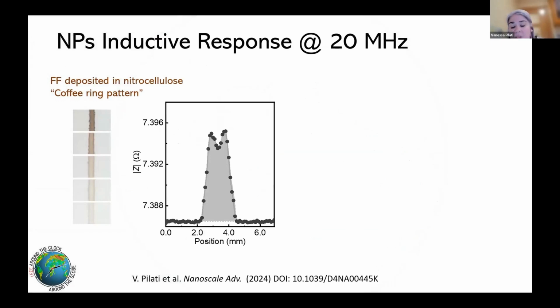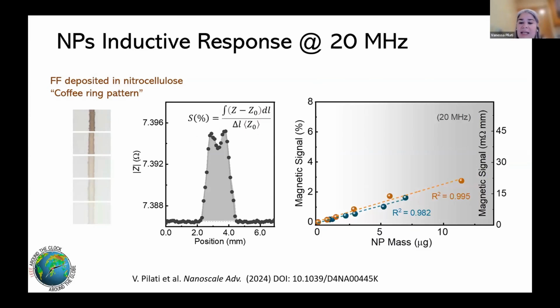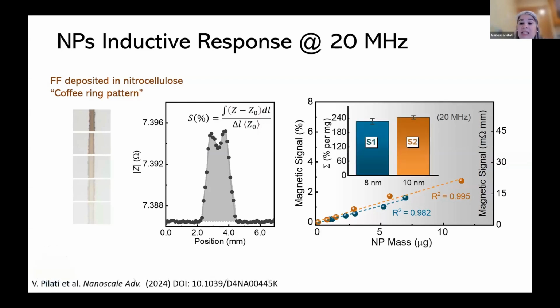We printed different lines, different concentrations of ferrofluid to have different mass of deposited nanoparticles, and we measured the signal of these lines to mimic a test line. We measured the magnetic signal as a function of the deposited nanoparticles mass, and we can see a linear trend. The best linear fit provides us values for the slope, which is the sensitivity for magnetic detection, which represents how much magnetic signal we can achieve with the mass of nanoparticles. So we can see that the large manganese ferrite nanoparticles provide a large sensitivity, so they are more sensitive for detection.